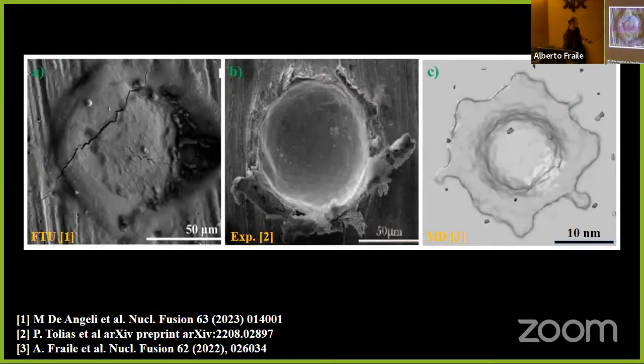This is an actual crater in a tokamak, in the plasma-facing material that is generally tungsten. So tungsten is the main candidate for plasma-facing materials in ITER and beyond. This is an example of a crater in tungsten in a dedicated experiment. So it's an impact of tungsten particles in tungsten. And the one on the right is the simulation using MD. Of course, we are not in the same scale. Here, the craters are microns in size, and we are in this nanometer scale, but we are in the same scale if we look at the kinetic energies.